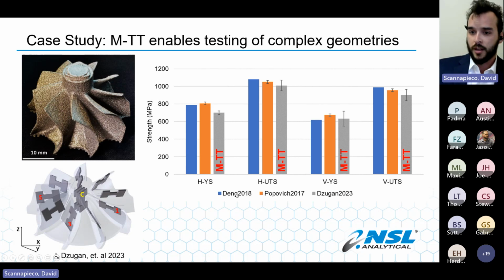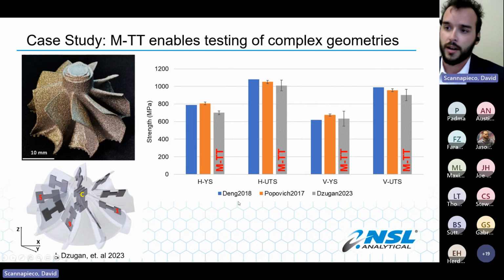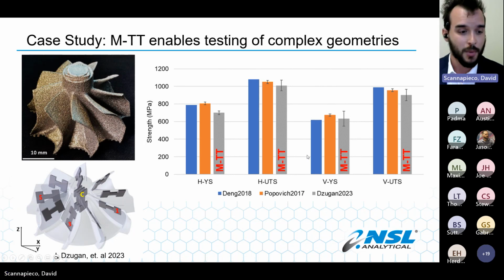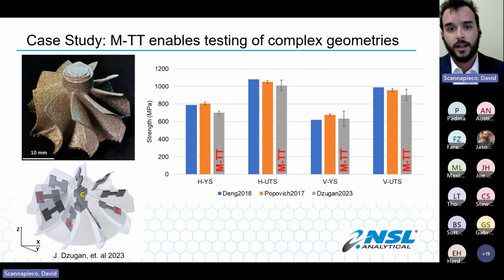And you can see, compared to two other literature sources that compare the Inconel 718 properties here, our miniature tensile specimens are performing on par, which is a great discovery. So we have complex shapes, but now we can test them, well, not no matter what, but even if they get very thin walled or very small component wise.